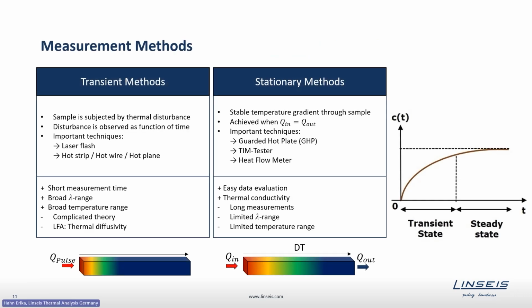In general, there are two methods or two classes of methods how to measure the thermal conductivity. We have the transient methods and the stationary methods. Within the transient methods, the sample is subjected to a thermal disturbance, and the disturbance is then observed as a function of time. To this method, also the laser flash belongs. An advantage is, as we directly have a look onto the sample when bringing in a thermal disturbance, the measurement times are very short. In addition to that, the transient methods typically allow a broad thermal conductivity as well as broad temperature range. A disadvantage here is that the theory behind the evaluation is typically quite complicated, and as we will see later on, the LFA firstly measures only the diffusivity.